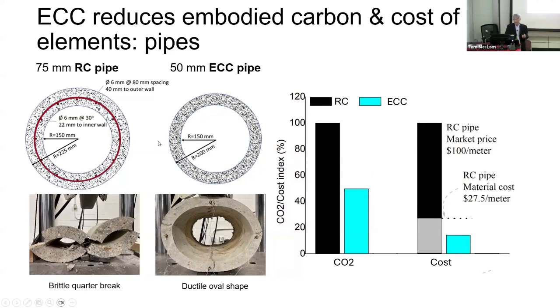Reducing the wall thickness, as a result, reduces the amount of material required. And yet, with these changes, elimination of steel reinforcement and thinning down the pipe wall, it actually performs better under diametric loading. Instead of brittle collapse into quarters, in the case of steel reinforced concrete, it actually deformed into an oval shape. And what I don't have time to show you is that we also did permeability studies. So we put water inside this greatly deformed pipe. The water did not leak.